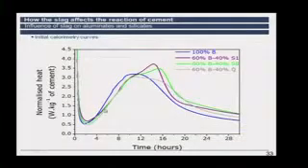So the effect we have on the aluminate reaction, we can see again in terms of the slag. Here in blue, we have the original Portland cement, and in grey, we have an addition of quartz, which has a very similar shape to the blue curve, but you see again the reaction extends longer beyond the peak and ends up being slightly higher. This is just a pure filler effect.